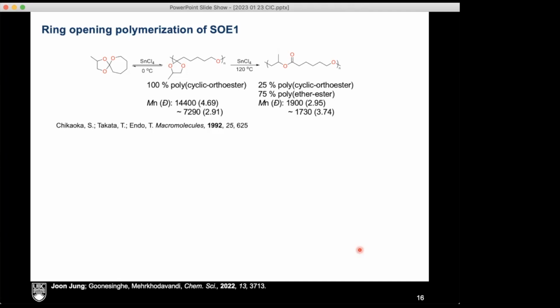applications. But what was kind of sad about the literature data was that when you take these and you take a Lewis acid and you try to polymerize them, this ring opens first. You get the mono-ring opened product with pretty large dispersity. And then when you heat this up quite a bit, then you can polymerize the second ring. It's harder, but now you're getting really low molecular weights with quite broad dispersity, and you're getting a mixture of the mono and the bis polymerized